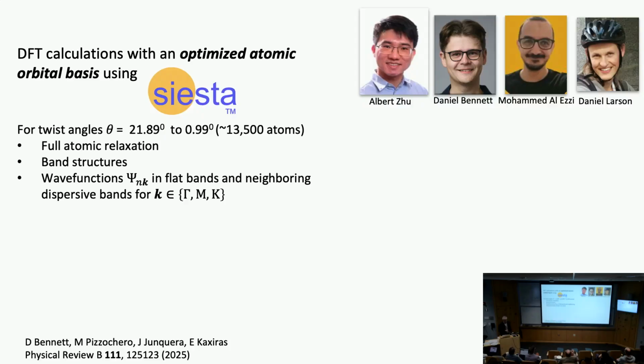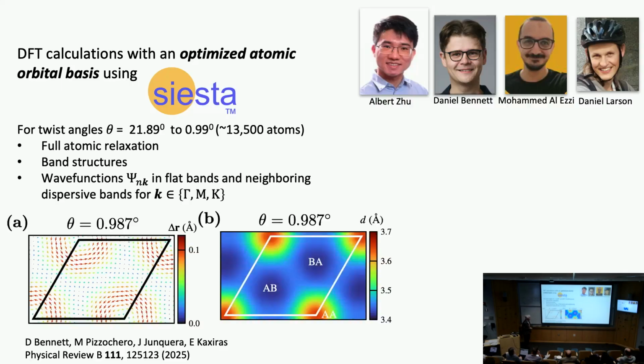Now, in the last year or so, by some technical improvements and advances, we have been able to do band structure calculations for twist angles all the way down to about 1 degree, a little bit below 1 degree, corresponding to 13,500 atoms, including full atomic relaxation, band structures, and all the information about wave functions in the flat bands and the neighboring states separated by the band gaps that are dispersive bands, have much higher dispersion than the flat band. So these are the group members who are responsible for this, and I'll show you some pictures describing all this.